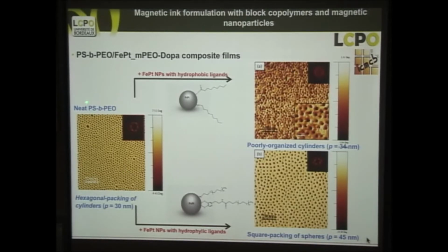Here, this copolymer is polystyrene-polyethylene oxide. This is hydrophobic, this is hydrophilic, and the hydrophilic part is the spheres inside here. So when we put the hydrophobic particles, we found them at the edges of the interfaces between the spheres and the matrix, which is the polystyrene. However, when we make them hydrophilic, they go inside the microdomains.